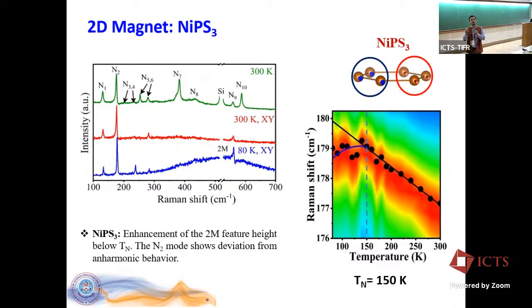There was a report which also said that the monolayer doesn't show antiferromagnetic ordering, and Raman was one of the tools, but then the NTU group, Qihua Xiong, did an extensive study and showed that even in monolayer there is antiferromagnetic ordering. The previous observations were a little inconclusive, mainly because the monolayer crystal symmetry and the bilayer-onwards crystal symmetry are different. And just because of the crystal symmetry, the Raman signature becomes slightly different, and that's where one has to be very careful. Okay, so anyway, the point is even NiPS3 has magnetic ordering even at single layer, okay? And the signatures are in the form of this magnon and the peak splitting.